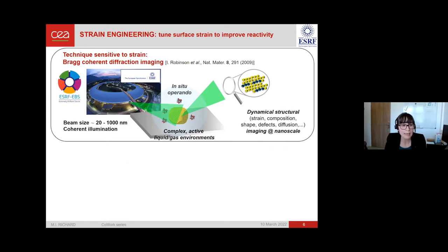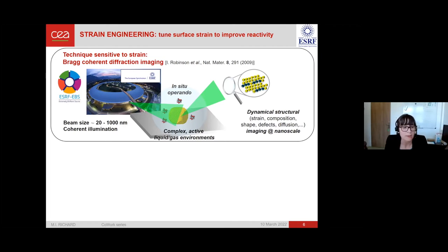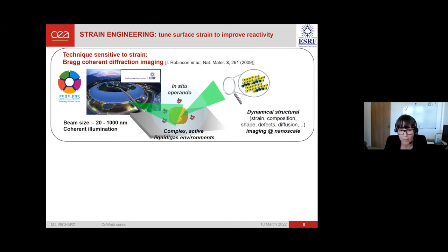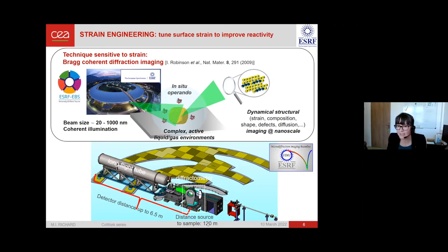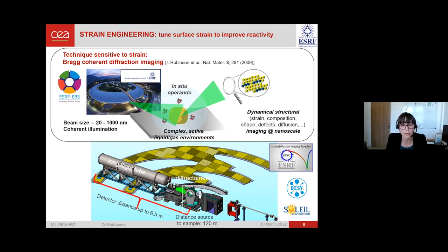We have access to a technique called Bragg coherent diffraction imaging, developed about 10 years ago by Ian Robinson and co-workers. It requires coherent illumination and a beam size larger than the particle. It can be applied in-situ operando in complex active liquid and gas environments, providing dynamical structural imaging at the nanoscale — giving access to strain, composition, shape, defects, and diffusion. Most experiments are performed at the ID-1 beamline, with the diffractometer positioned about 120 meters from the source. I also apply this technique at other synchrotrons such as DESY and Soleil.